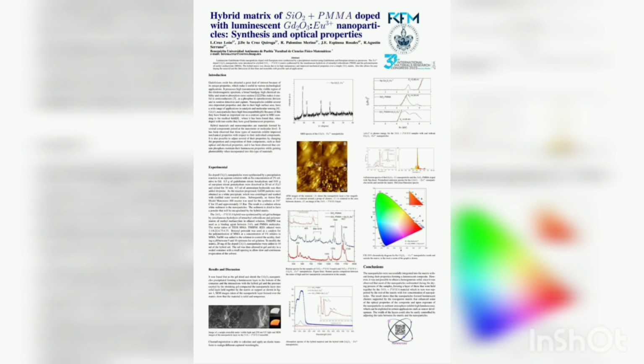On the other hand, the hybrid matrix we synthesized by the sol-gel technique by the simultaneous hydrolysis of tetraethyl orthosilicate and the polymerization of methyl methacrylate in an ethanol solution. We also use another component to start the polymerization of the methyl methacrylate, that is the benzoyl peroxide. We use an agent to bind the silicon and the PMMA, and we also use sodium hydroxide to control the acidity of our solution.